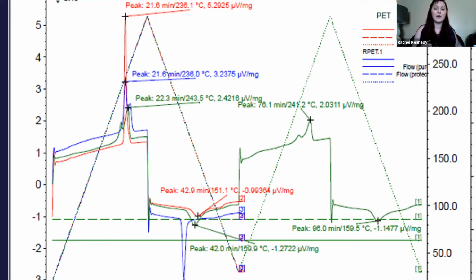One of the key points Walter was talking about earlier was that the melting of your sheath has to be different to your core. So if you look closely at your green line here, you hopefully can see that before the dual peak at the red and blue line, there is a small peak beforehand in the green. This is the melting of the sheath.